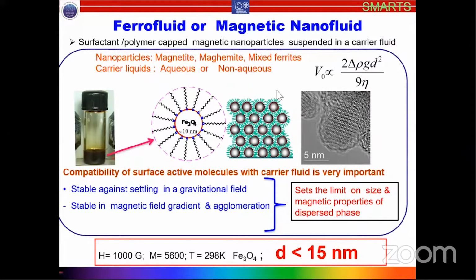You can have different types of particles in this kind of magnetic fluid. It can be magnetite, Fe3O4, gamma Fe2O3, or cobalt, nickel, ferrites, that is mixed ferrites. And you can also disperse these particles in different fluids. It can be dispersed in water, or non-aqueous fluids like oil. And as I told you, size restriction comes from the fact that the particles have to remain suspended and they have to be stable against strong dipolar interaction and aggregation.